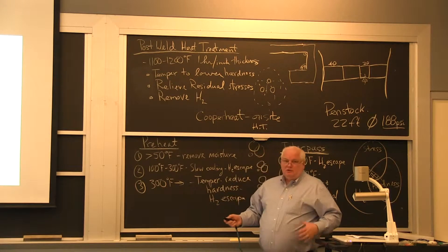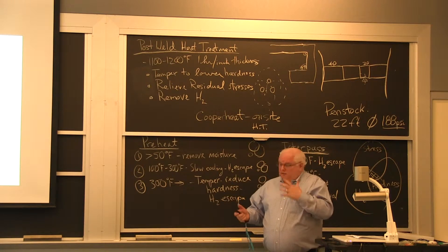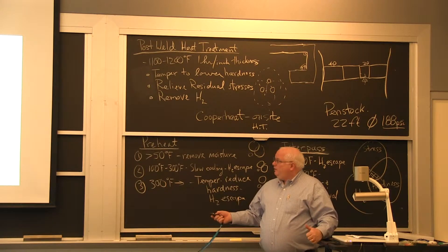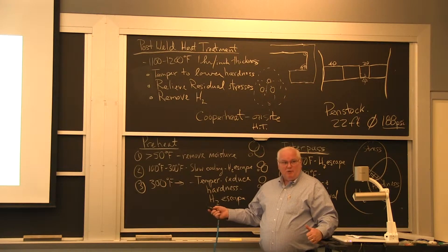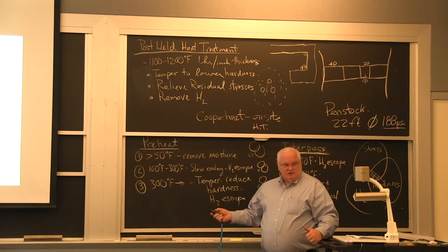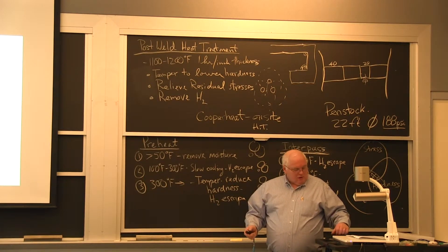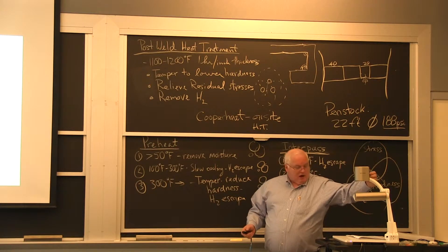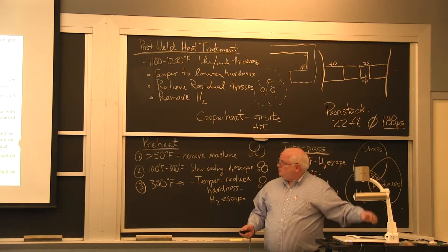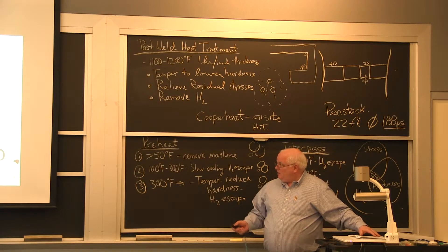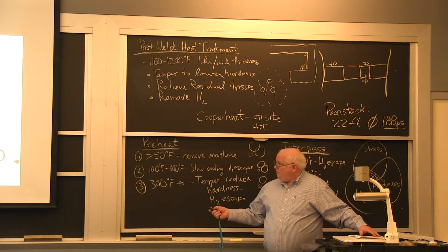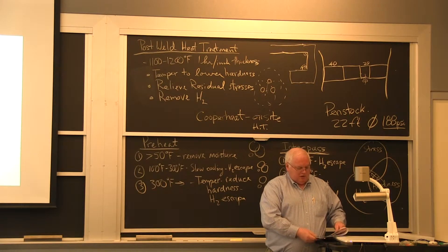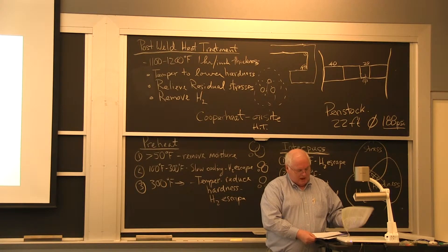And this is just a formula which no one will tell you is the hardenability, but in fact it's just a formula for the hardenability of the steel. So when these people asked me to develop a welding procedure the first thing I want to know is the chemistry, because I've got to figure out a carbon and a carbon equivalent. And then I need to know the thickness. So if my method is going to be hydrogen control, which is this, in this section it says I then have to go to figure I1, this is appendix I, and to figure out what zone I'm in.